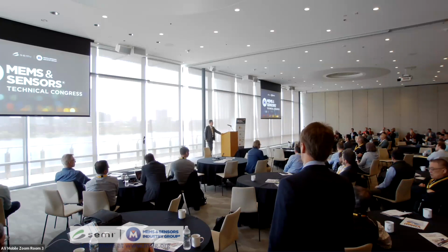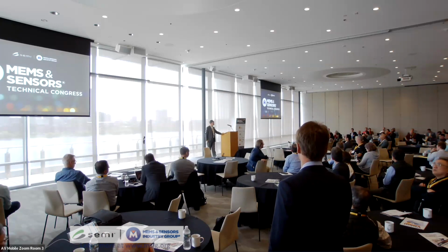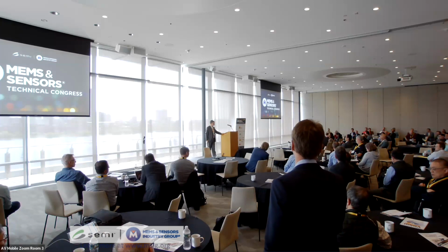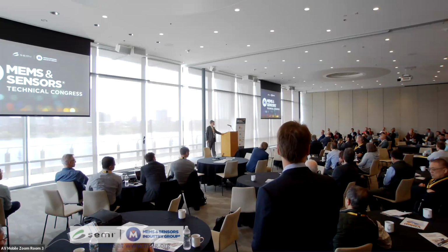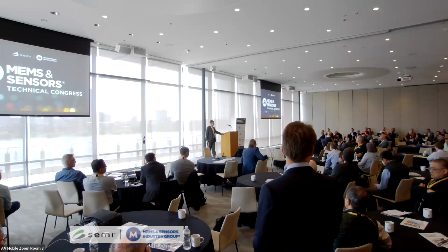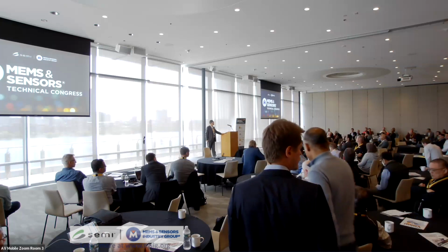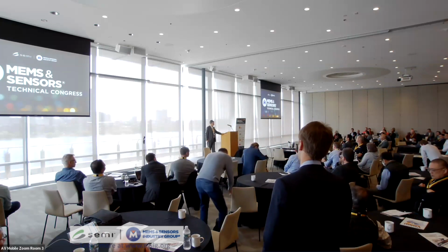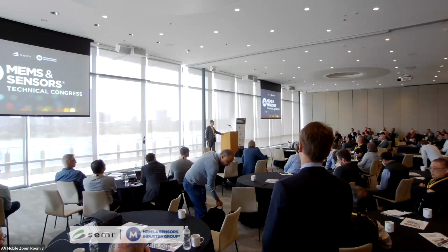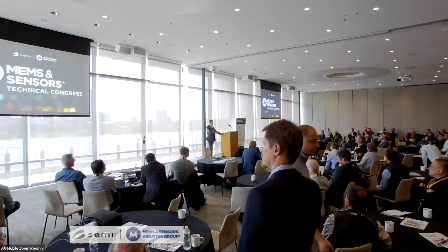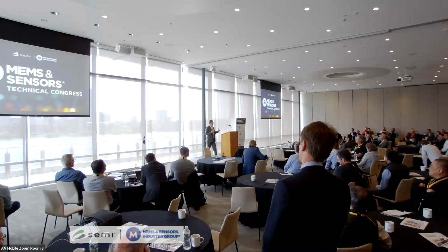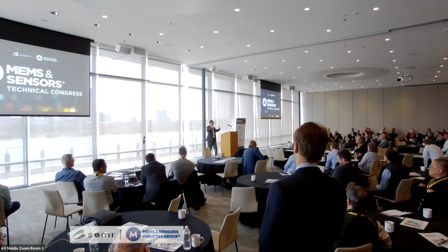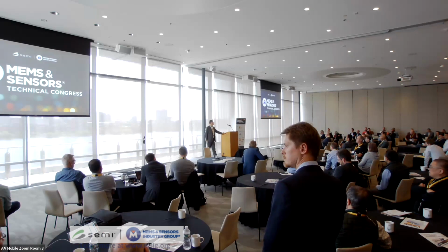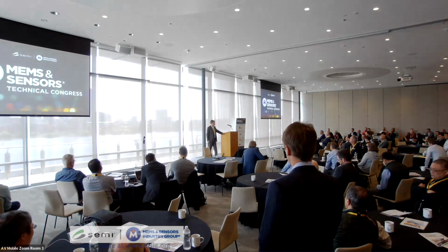Great question. I got a question. You said when you do the bonding, you get your alkali depleted on the surface, a thin layer of silicon dioxide. You said that you're causing the mismatch, because silicon dioxide CTE is almost zero, so you're causing wafer bowing. How thick is that depletion layer? It can be on the order of a micron. I actually provided a reference where people did detailed modeling to see how the thin layer CTE can impact overall stress. So we have not done that ourselves, but there's literature that describes this.